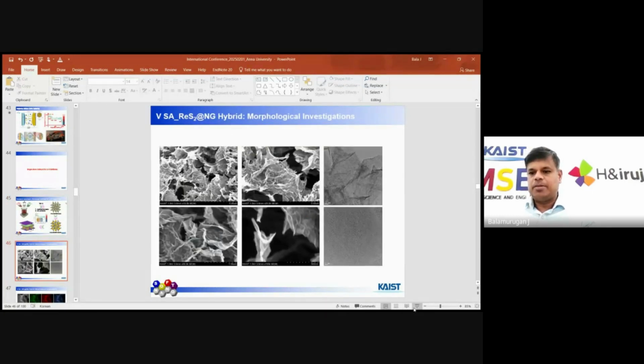After fabricating the material, we confirmed it by morphological investigation. You can see there is homogeneous distribution of the single atom with the metal sulfides. We cannot see any metal nanoparticle, even at the 2 nanometer scale bar. You can see there is no metal nanoparticle. We cannot see a single atom by TEM, but from the STEM we can see it.